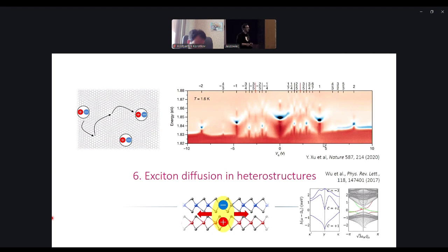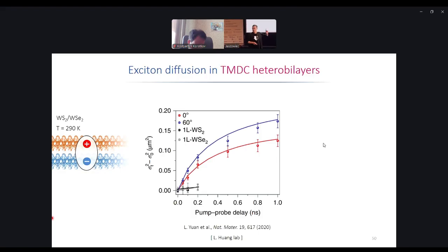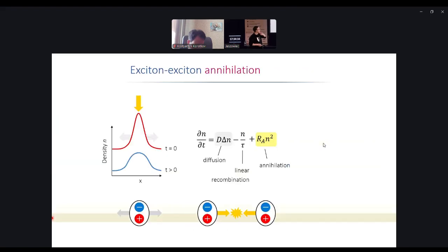Yeah. In a Moiré system, what would you expect? A system like this on the left, we have local minima. What would you expect there? Hopping, localization, thermal activation, potentially slower transport. The more surprising it was that in one of the early measurements, and this is from the lab of Libai Huang, the opposite was observed. And the system is complicated. It's not necessarily universal, but in this observation, interlayer excitons can actually be much faster than monolayer ones. And one of the ways to think about it is the following.